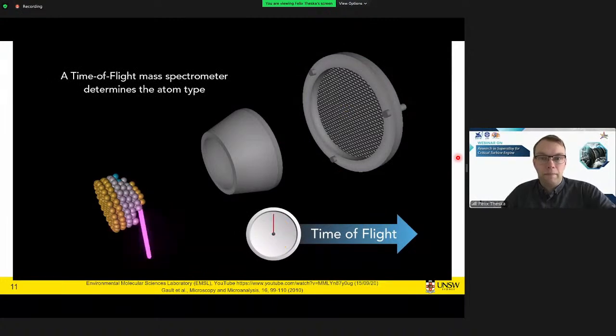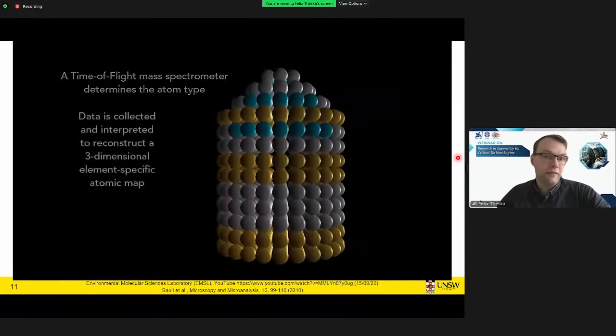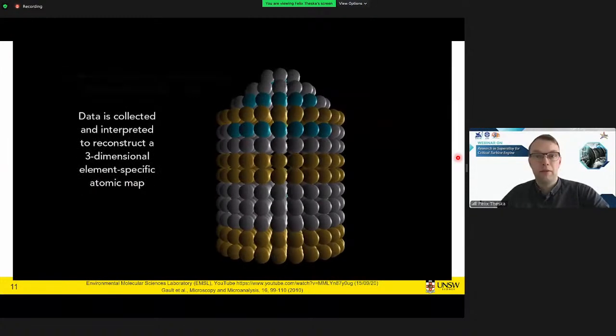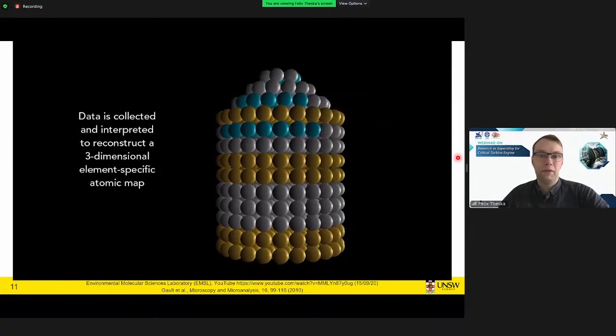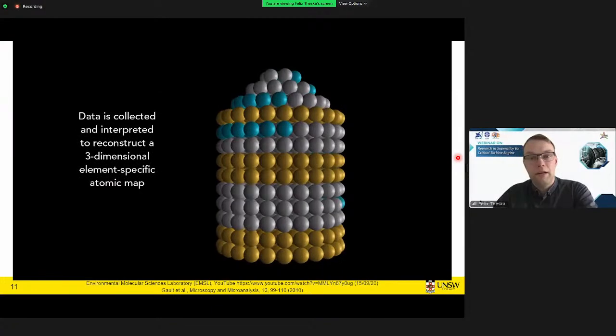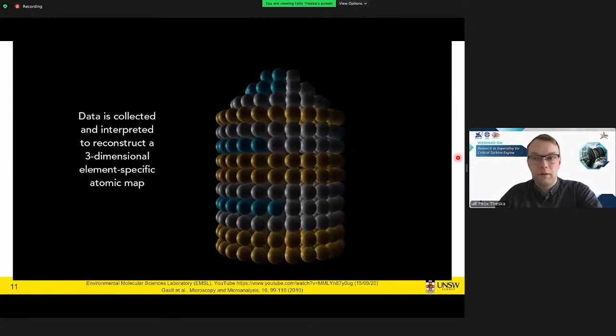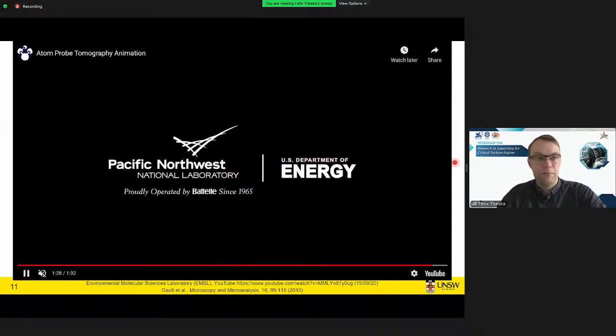Now you can see, because we pulse and then we can measure the time of flight, we also have a mass spectrum in the Atomprobe, which is very convenient because not only do we get the X, Y, and Z coordinates, but also the type of element where it used to sit. And then we get these very nice three-dimensional atom maps.